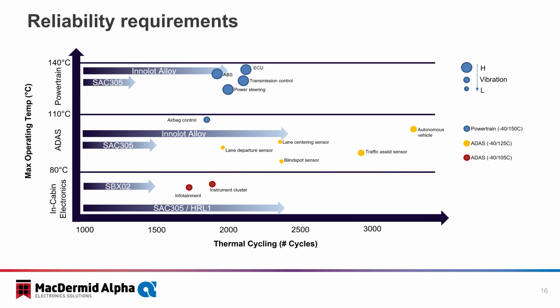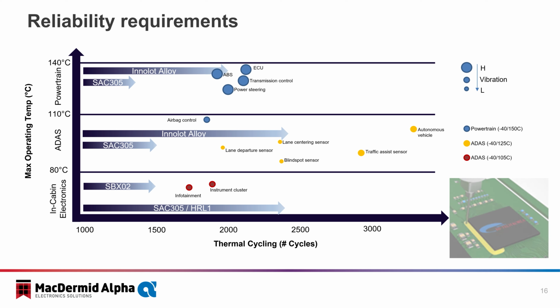And again, as I mentioned earlier, car makers are putting extremely stringent test requirements on ADAS systems, and it's not a surprise. From this chart, you can see that the originally chosen alloy, the SAC 305 or tin silver copper alloy, cannot withstand the thermal cycle requirements used for things like lane departure sensors and blind spot sensors. You have to use an enhanced alloy like the Innolot. And then as we progress to higher levels of autonomy, level 4, level 5, with traffic assist sensors and autonomous driving vehicles, it is likely that you will have to use an underfill or corner fill in conjunction with the Innolot alloy. Currently, our development labs have testing to analyze the results of these combined materials.